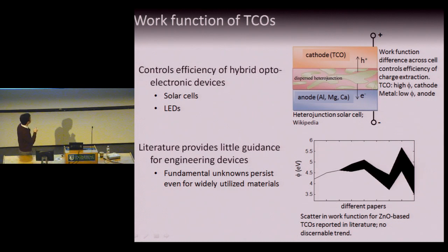The fact that the hole goes in one direction and the electron goes in another direction is largely determined by the fact that these two materials are meant to have very different work functions. And the efficiency of this device is to a large extent controlled by the difference. It's controlled by many things, but one of the important factors is the difference in work function between these two materials. So if I were interested in improving the efficiency of present-day solar photovoltaic thin film technology, I would want to get this work function as high as possible, which is in itself a worthy research goal.